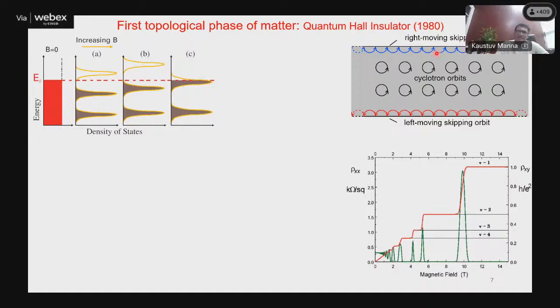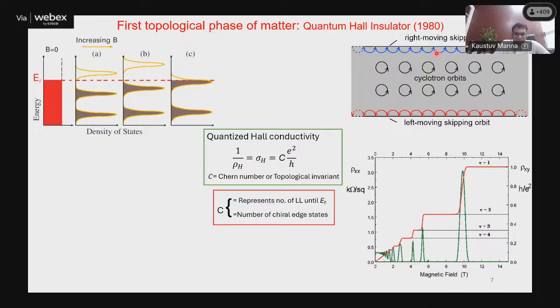Chiral edge state, helical edge state, same thing. Different terminologies, different papers, it represents the same thing. Now, when we do the real experiment, we can calculate the resistivity. From there we can calculate the conductivity, and if we plot it in this form like e²/h, then what we find is that this plateau is an integer number of e²/h.